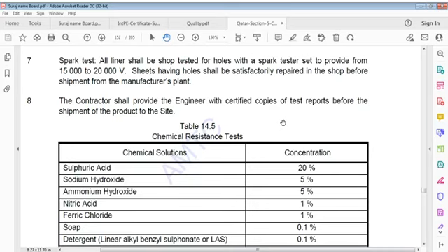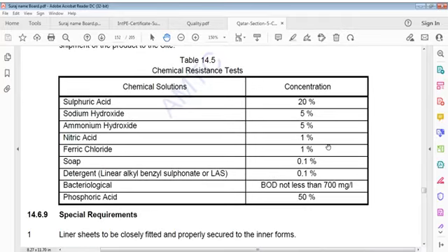All liner shall be shop tested for holes with a spark tester set to provide from 15,000 to 20,000 volts. Sheets having holes shall be satisfactorily repaired in shop before shipment from manufacturer plant. Contractor shall provide the engineer with certified copies of test reports before shipment of product to site.